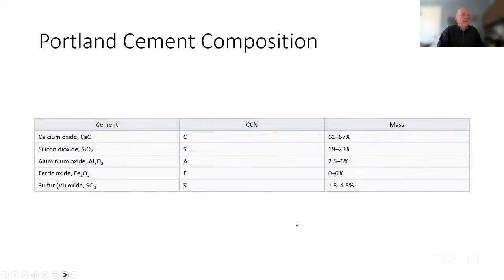Okay, so here's a typical composition. 60% range for calcium oxide or lime. About 20% silicon dioxide, 2.5 to 6% of aluminum oxide. Remember, it accelerates hardening, gives you a little bit of early strength. Likewise, 0 to 6% of ferric oxide, and then you have a little bit of this sulfur in there. Okay, and the sulfur will slow things down. It's used to moderate how quickly hardening occurs.